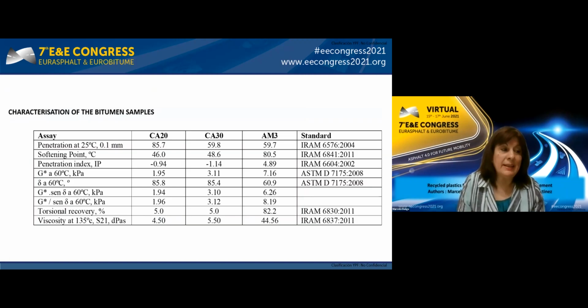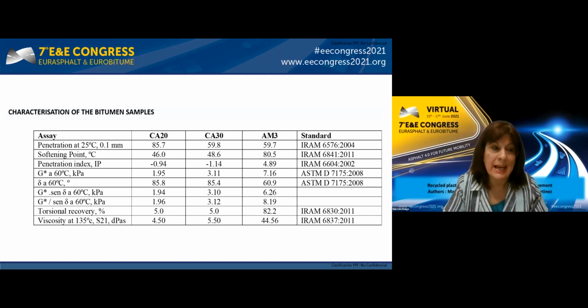In a previous lab study conducted before the field test, a softer CA20 bitumen was used to incorporate the recycled plastic both in pellets and in powder, in 4 increasing amounts from 1 to 4%. The samples were compared with 2 other bitumen control samples, which were a conventional CA30 bitumen and a commercially available polymer modified bitumen named AM3. This bitumen met the respective Argentinian specification. The physical and rheological characteristics of these 3 bitumens are shown in this slide.